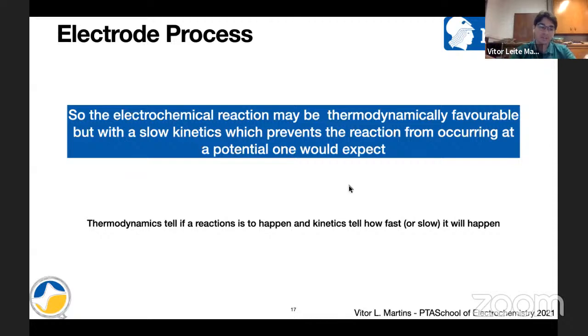So what will the catalytic effect do? It will help the kinetics of this reaction to occur. So you have the same reaction, but using different electrodes, and the reaction is fast in one type of electrode and slow in another type of electrode. So we have a catalytic reaction occurring when you use platinum. So that's why people use platinum to produce hydrogen, right? It's really a catalytic reaction over there.